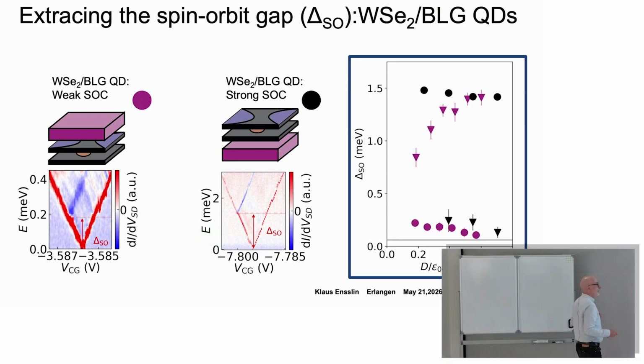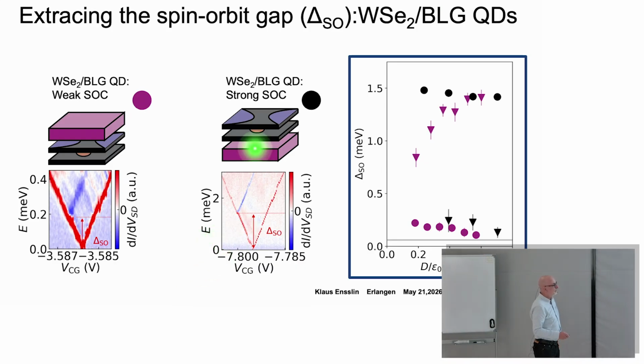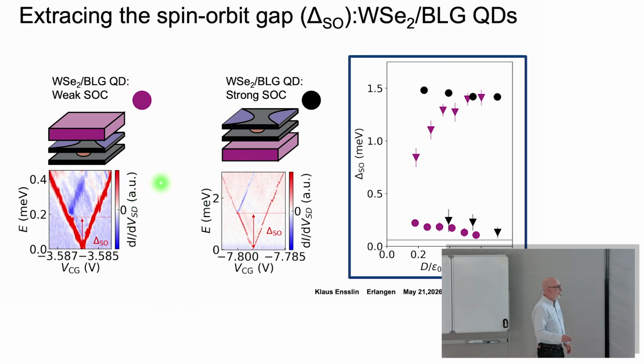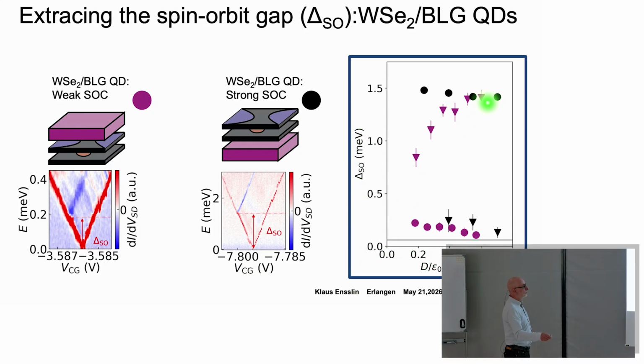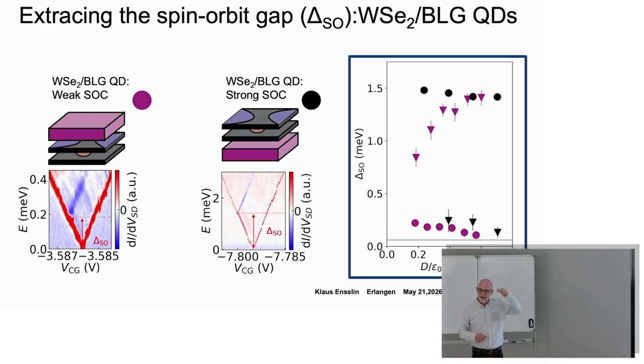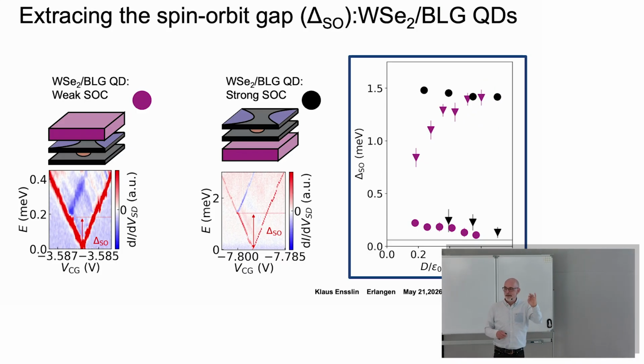Okay. Now you can make many quantum dots, and you can do a lot of QPCs, and we call it spin-orbit interaction, the splitting here, as a function of the electric field that you apply, and you see you can tune it to 1.5 milli-electron volts. Let me put that in perspective. The bare spin-orbit interaction in graphene, as I said, is down here. It's about 100 microelectron volt.